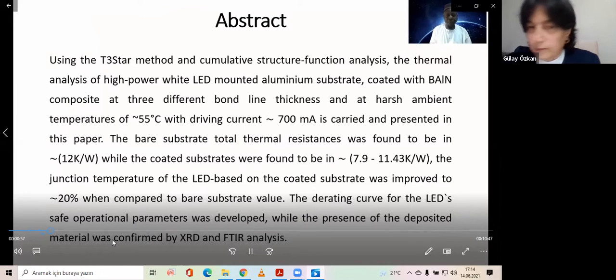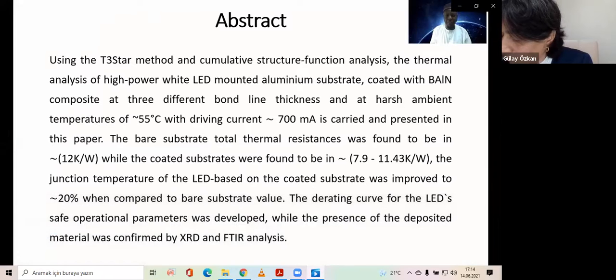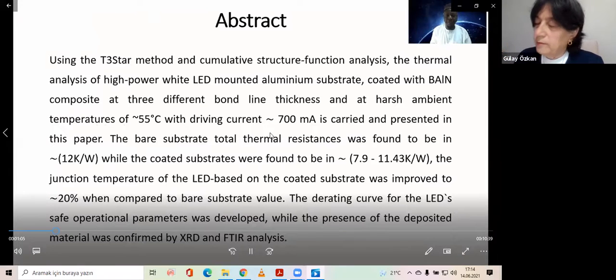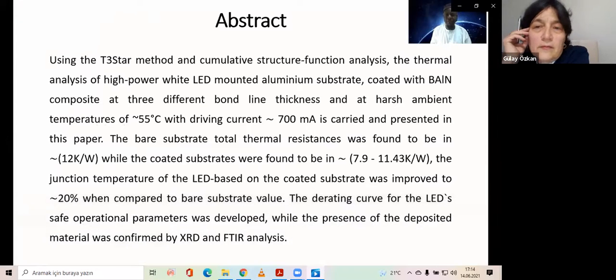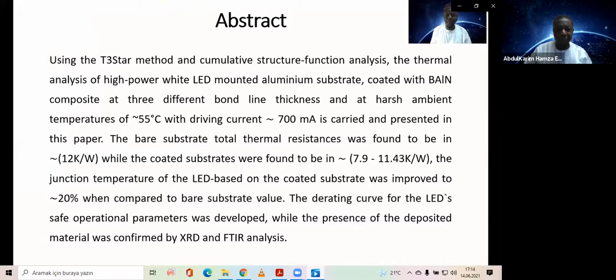Abstract. Using the thermal transient testing method and cumulative structure function analysis, the thermal analysis of a high power LED mounted on a bare aluminum substrate and a coated aluminum substrate at 3 different bond line thicknesses and at a harsh ambient temperature of 55 degrees C with a high driving current of 700 milliamp is carried out and presented in this paper.